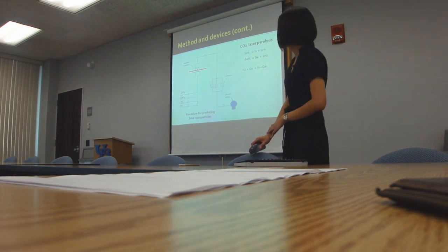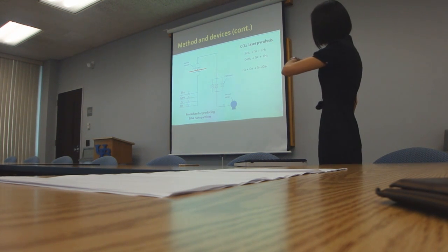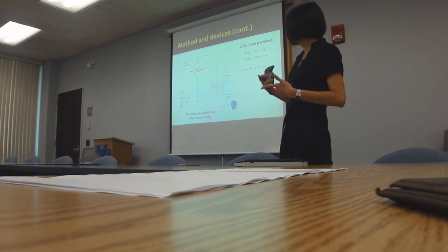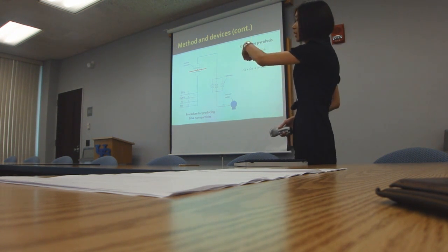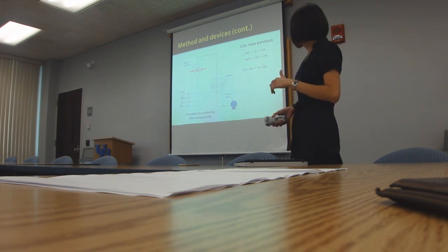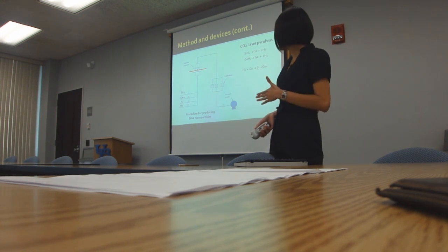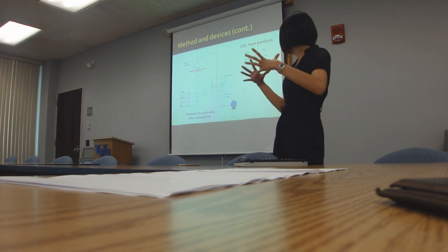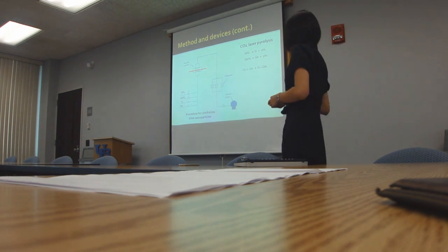We use CO2 laser pyrolysis to produce the particles. This is a schematic of the setup in our lab. Silane gas, germane gas, hydrogen, and helium are all added to the reaction chamber, where a laser beam shoots through. Silane gas is decomposed to silicon particles, and germane gas is decomposed to germanium particles. All those particles will diffuse into each other to produce bigger silicon-germanium alloy nanoparticles.